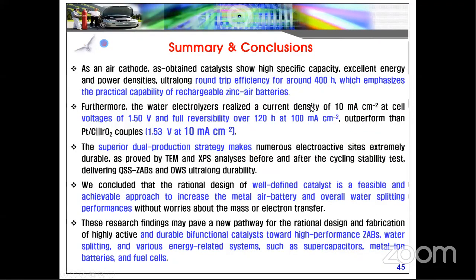And our catalyst showed stable round trip efficiency for 400 hours in the zinc air battery, and in water splitting also we achieved 1.5 volts, because we need to go towards 1.23 volts, but everyone is trying for that. Our catalyst outperformed the commercial couple like platinum on carbon and iridium.